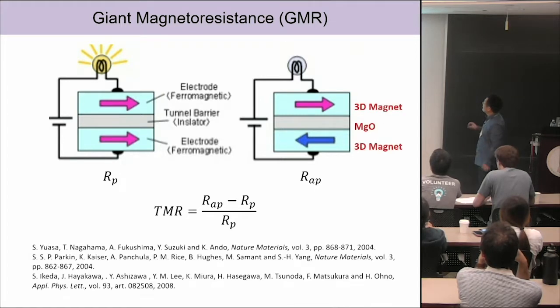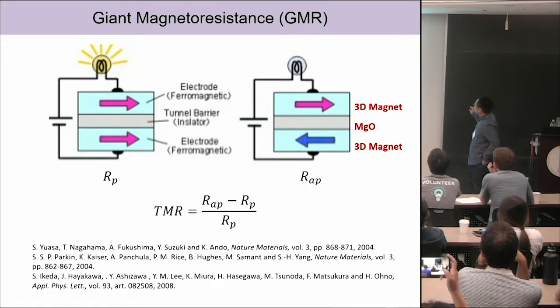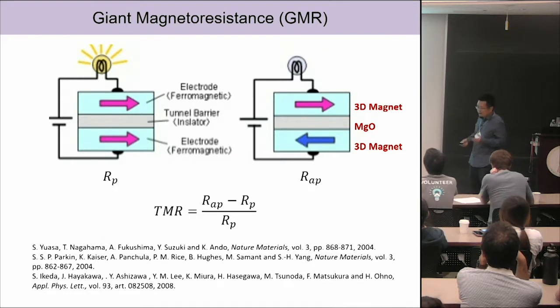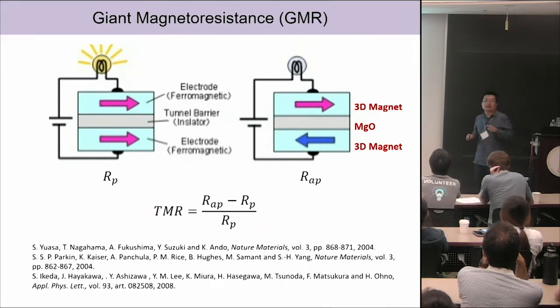Usually the tunnel barrier is critical for the TMR, and for the state of the art, they use MgO, and then you can match the momentum, the scattering momentum, etc. of the MgO by picking particular 3D magnets. So the state of the art for this TMR, for this particular system, is on the order of 500% at room temperature and about 1300% at low temperature. Okay.